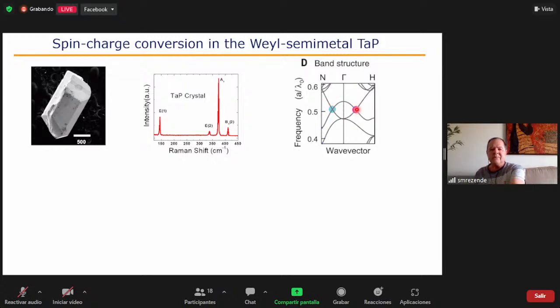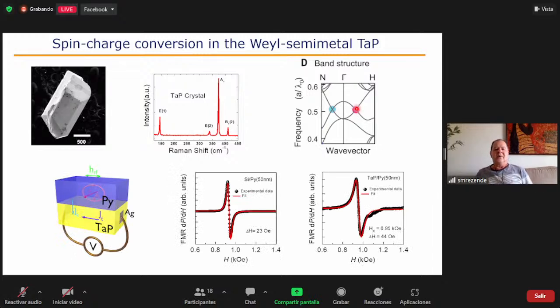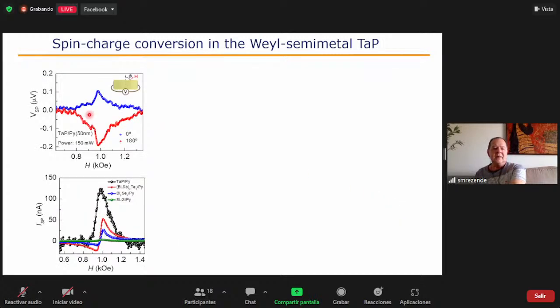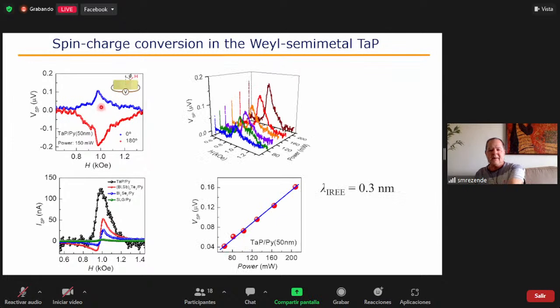and this is a negative Dirac particle. Well, it turns out that this also has the property of converting spin currents into charge current. The experiment was done by depositing a permalloy film on the tantalum phosphide crystal. This is the FMR of the material. This is the voltage. It's not very beautiful like the previous ones. It's also not symmetric, but this was done at several powers and frequencies, and we confirm that this is the spin to charge conversion,